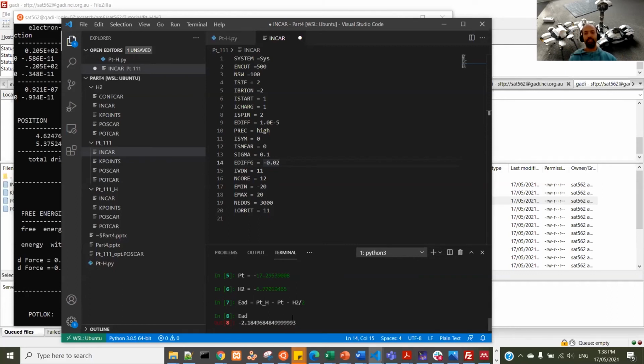one approximation I've done here as well is that I have modeled 3 atoms only in our platinum slab. Actually, in typical calculations, you want to have that slab thicker, like 6 atoms or even 9 atoms deep. And then you freeze the bottom 3 or maybe the bottom 4. And then you can have improved accuracy. But the approximations I've done here in this calculation were just meant to make things simpler and quicker, as you can see here.